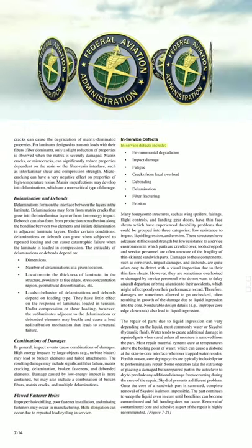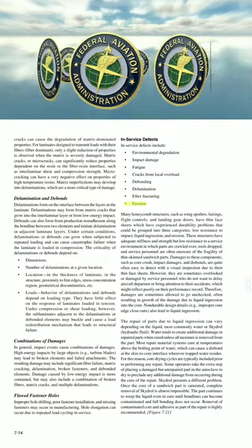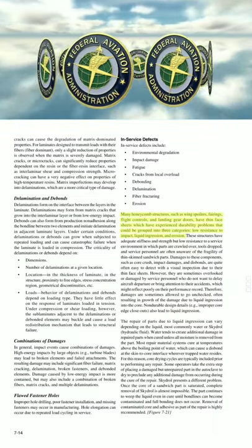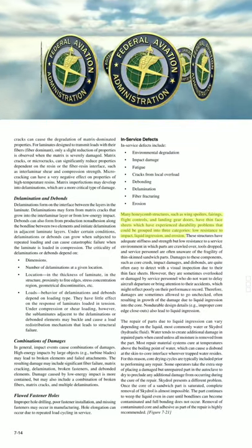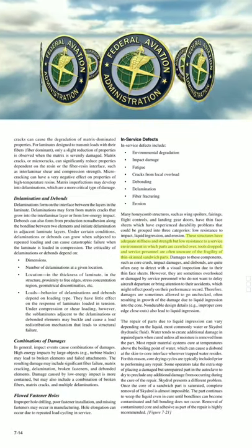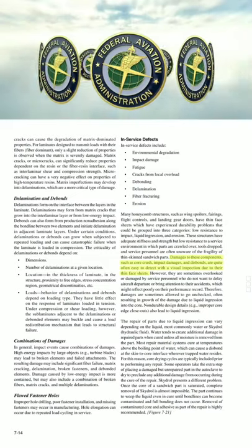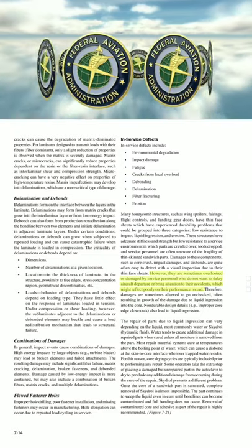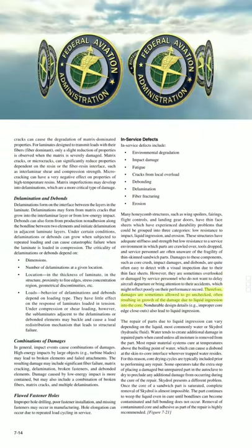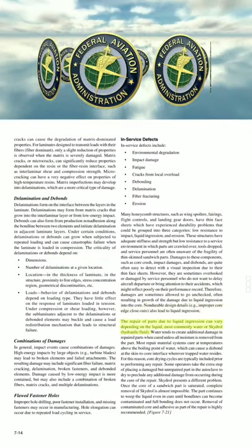In-service defects include environmental degradation, impact damage, fatigue, cracks from local overload, debonding, delamination, fiber fracturing, and erosion. Many honeycomb structures such as wing spoilers, fairings, flight controls, and landing gear doors have thin face sheets which have experienced durability problems in three categories: low resistance to impact, liquid ingression, and erosion. These structures have adequate stiffness and strength, but low resistance to a service environment in which parts are crawled over and tools dropped, while service personnel are often unaware of the fragility of thin-skinned sandwich parts. Damages such as core crush, impact damage, and disbonds are quite often not detectable visually due to thin face sheets.